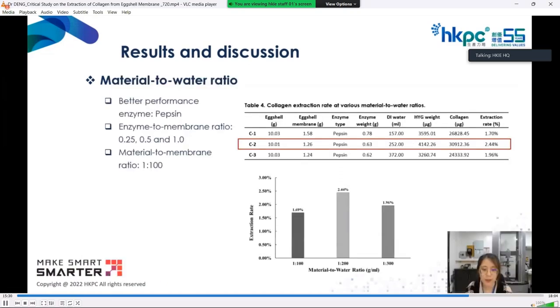As shown in Table 4, when the material to water ratio changes from 1 to 100 to 1 to 200, the collagen extraction rate increased from 1.70% to 2.44%. However, when the ratio reached 300, the collagen extraction rate decreased to 1.96%.